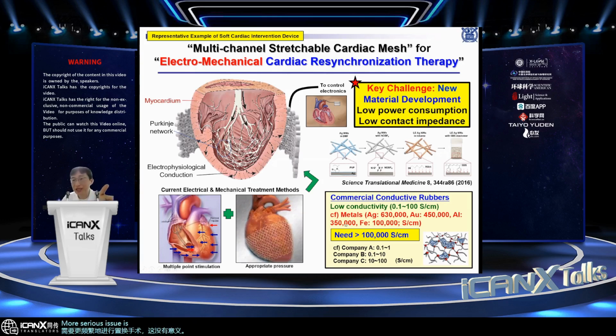A more serious issue is contact impedance. If the resistance is high, that means the contact impedance will also be high. And if the contact impedance is high, then when we want to inject electric current into the cardiac tissue, we have to apply high voltage because of the high contact impedance, high contact AC resistance. And that will cause very large power consumption, as well as electrical stimulation fatigue accumulation. So both are very bad situations.